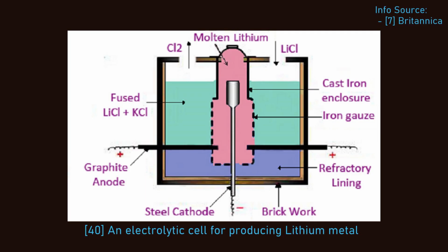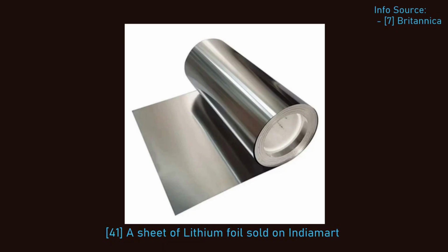At this point, there are still contaminants in it, and it is only 97% pure lithium. The lithium is then ladled from the cell and poured into a mold that is slightly above its melting temperature. From here it is melted again, and the insoluble materials in its molten form float to the surface, or sink to the bottom of a pot and are removed. This remelting step reduces the amount of potassium in the material to less than 100 parts per million. While harder than other alkali metals, lithium is still softer than lead, and it can either be rolled into sheets or drawn into wire.